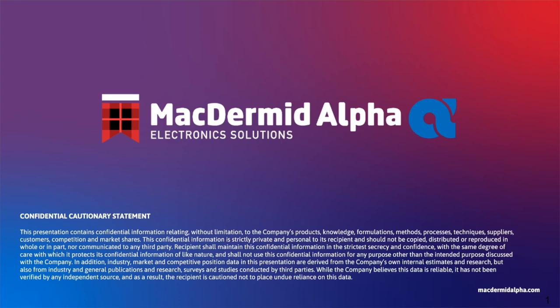So as your package may have a tendency to go through these thermal exposures or thermal cycling, for example, where we are cycling from a low temperature to high temperature and back and forth, there is also moisture exposure. Organic substrates may have more tendency to absorb moisture inherently. So you need to have chemistries that are resistant to picking up that moisture and then affecting the properties. So you find the right balance where your material has adequate moisture resistance, so it doesn't pick up moisture, and the modulus is tuned in that range where any of the stresses that the package may experience, and there will be different stresses between a lead frame and BGA, it can actually mitigate those stresses.